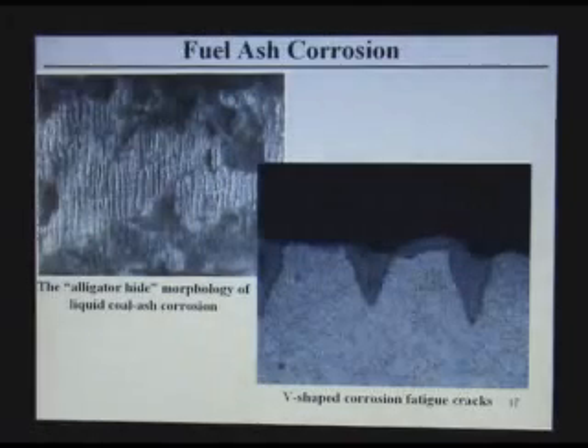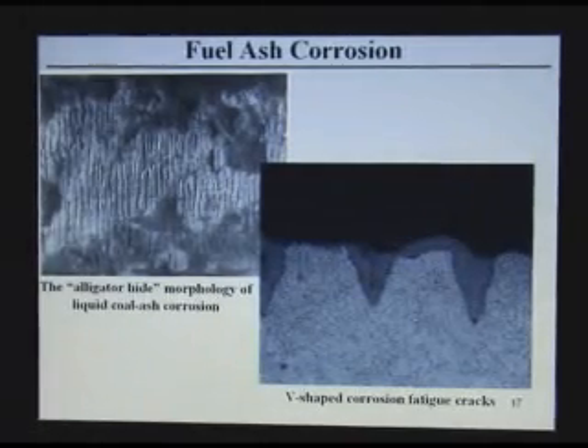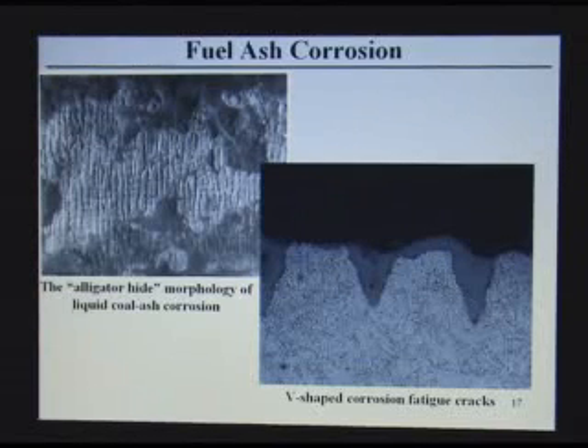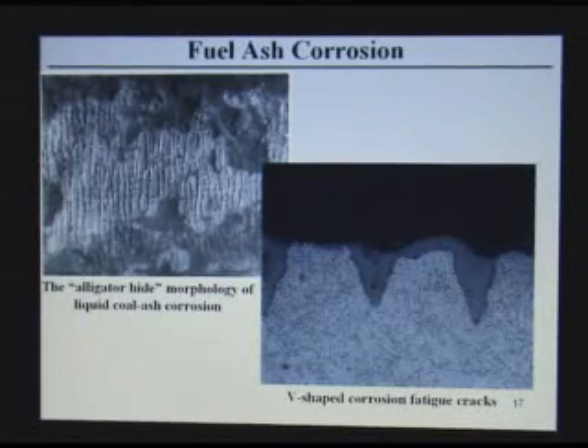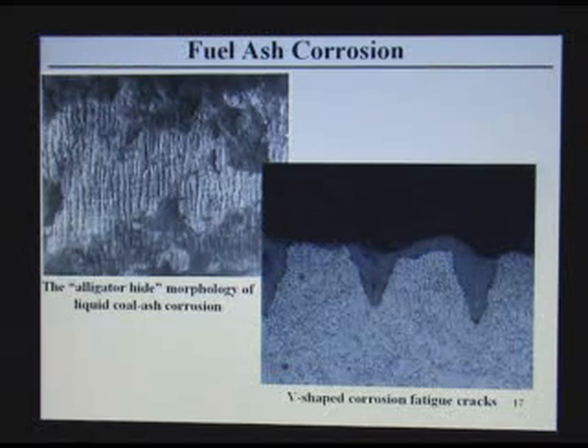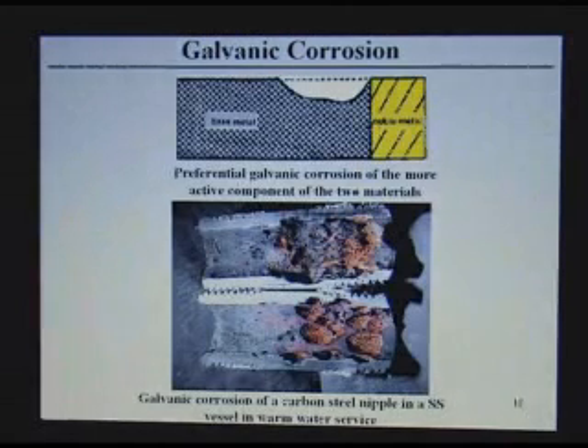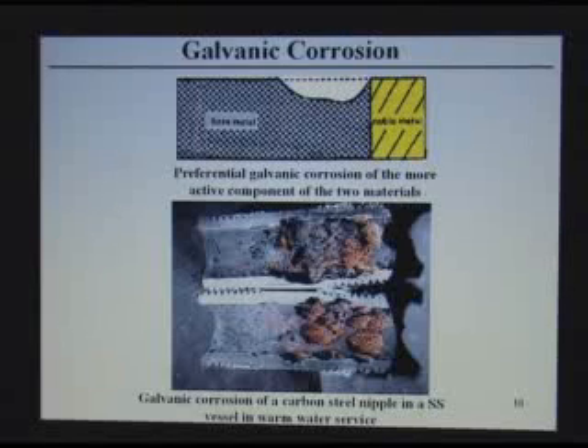This is the ash corrosion, which is from fuel oil that you burn in a heater, and it forms something like a ceramic type deposit, but it attacks the metal, and the metal gets lost. This is the example of galvanic corrosion. If you have a noble metal next to a non-noble metal, because of the galvanic action between these two metals, the least noble metal will corrode, and this is an example of what happened here.